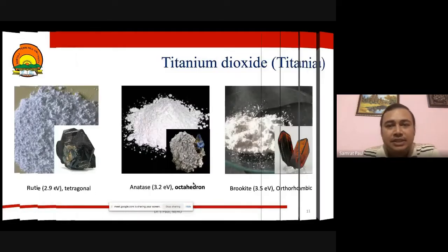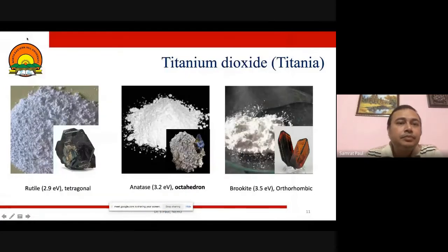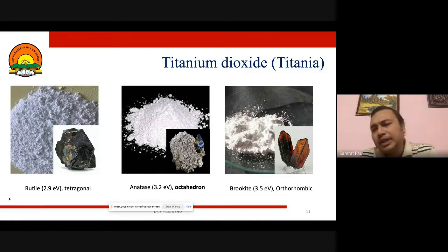Now let us come to synthesis. The first material that we will be talking about is titanium dioxide, or in short, it is also known as titania. So there are three types: rutile, anatase, and brookite. You can see rutile has 2.9 electron volt band gap. It is a tetragonal structure, whereas anatase has 3.2, and brookite has a slightly higher band gap, and it is not suitable for photovoltaic or photocatalytic activity.